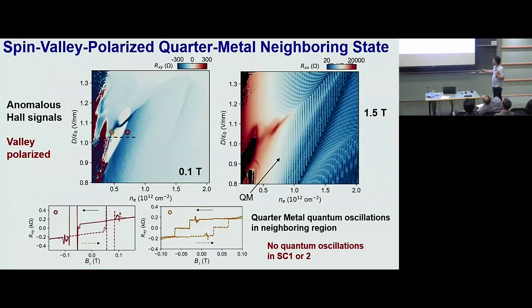And there's no obvious quantum oscillations in the SC1 and SC2 region. Right? Here's SC2, here's SC1. There's no quantum oscillation observed. We believe this may be due to the fact that this band is really, really flat. If you do a calculation of the effective mass, you probably get something like 2 or 3 times the bare electron mass. Okay, good.